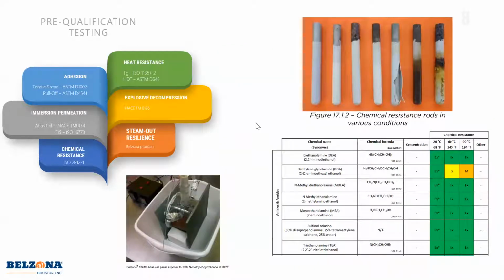Also, biggest question, all these pressure vessels are going to have some sort of chemicals. Can we handle the chemicals? Well, we do year-long testing. We coat these rods and we immerse them into a lot of different chemicals at different temperatures and concentrations. For them to have an excellent rating, they have to have no defects after 1 year. As you can see, these rods on the right here, that would be a fail. They have some cracking, some blistering, some delamination, so obviously that chemical ate away that coating. For it to be rated excellent, which is rated for full immersion, they have to look perfect when they come out, no defects.